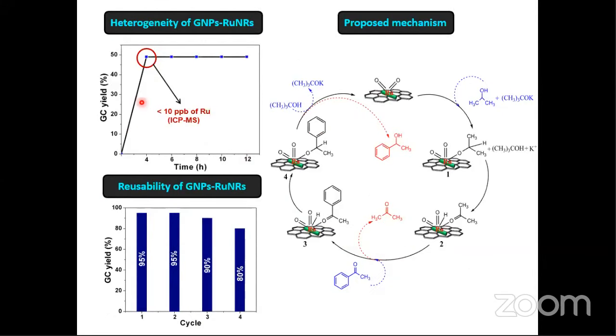Now you see, to know the leaching of ruthenium from the surface of graphene nanoplatelet, you see here, after 4 hours, the yield of the reaction is around 50%. After 4 hours, the catalyst was separated. The reaction was continued without the catalyst. There is no increase in the yield of the product, which indicates that the ruthenium, which is present on the surface of the support, only catalyzed the reaction.